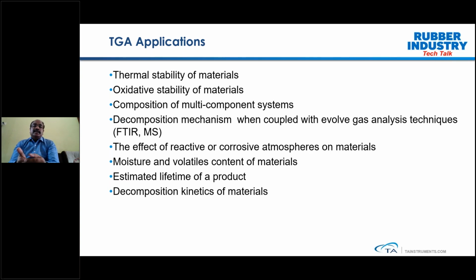And the third is the composition of a multi-component system. What we do is, as the polymeric materials, rubber polymers, consist of many components, as you know, it consists of high volatile components, and then we have the plasticizer, and then we have the polymeric component, and then filler, oils. All those things are mixed together. As we heat the sample, the components start evolving one by one, and that also can be coupled with the evolved gas analysis techniques.